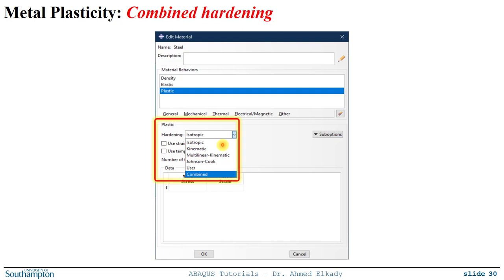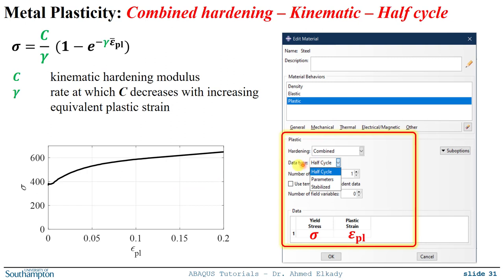So let's see how we can define a combined hardening rule in ABAQUS. Well, first thing, from the drop-down menu, you will need now to scroll all the way down and select combined. You will see another drop-down menu will appear that says data type. And what you need to define here is the kinematic component of the combined hardening rule. So how can we define the kinematic component? Well, ABAQUS defines the kinematic hardening using this equation. It relates the stress with the equivalent plastic strain. Notice here, this is the equivalent plastic strain. And this relates the two quantities using this exponential formula. And you have these two constants, C and gamma.